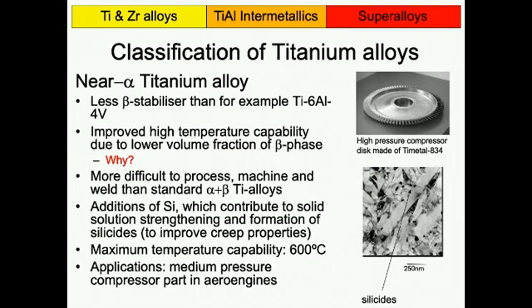You might actually say that. I think it could be an issue. I think you could probably go a bit higher before you see that. Because maybe above this temperature, the titanium oxide is not protecting anymore. Very good, very good. Titanium and zirconium have actually very poor oxidation properties at high temperatures. So oxidation is actually a big problem. So that's a limit. There's another limit, and that is that titanium is actually not burn resistant at very high temperatures. So it can ignite.